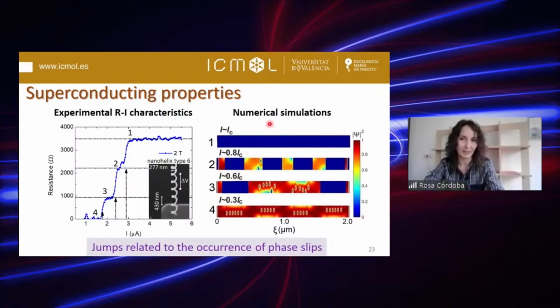You can see in this plot the superconducting order parameter at these 4 different regions, and at number 4 we are observing the vortex patterns on this structure, and how, when we increase the current, 2 phase slip regions emerge, inducing this jump in the resistance. And in region number 2, 2 more phase slip regions are emerging, producing the next step in the resistance. And I would like to remark that this phenomenon was not observed in planar structures, and it is giving us an idea of how we can tune and modify the superconducting properties in three-dimensional superconductors.